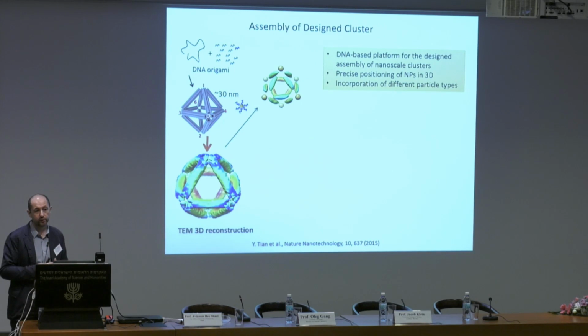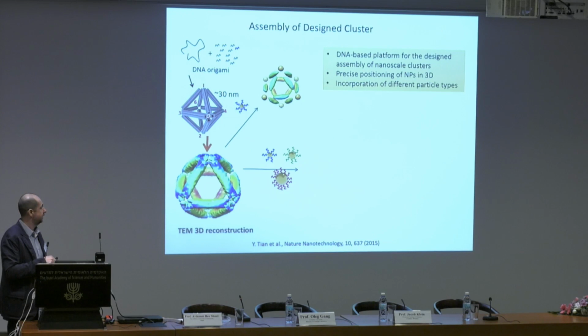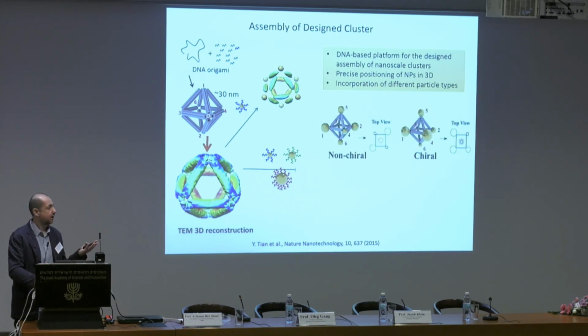And this is kind of like a supermolecule, but again, made out of particles, fully coordinated by this octahedra. Because we have full control and addressability, those 6 addresses can be the same. In this case, we have this type of situation, but they also can be different. For example, in this case, we will have 3 particles of different sizes, which have different DNA, and will have different complementarity. As a result, having the same underlying object, but repositioning or recoloring the bonds, we essentially can build non-chiral and chiral organizations from those 3 types of particles.